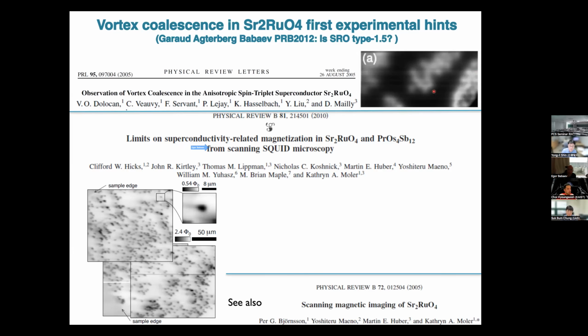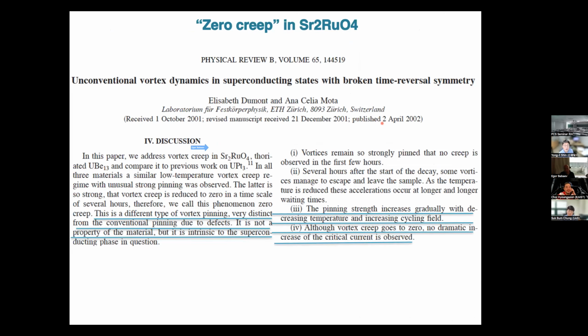So vortices form these fancy vortex clusters. And then it was voiced for a long time that there is inter-vortex attraction. But what is more interesting, there is a long-forgotten paper, which didn't say anything about inter-vortex attraction, that saw zero vortex creep in strontium ruthenate, but without any increase in critical currents. That precisely means a very different type of interpretation.